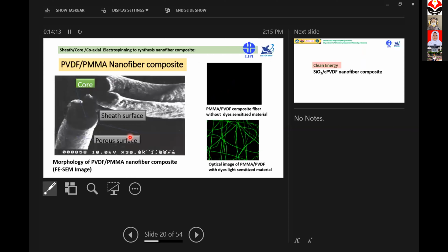Now, how to make nanofiber by using coaxial electrospinning composite. In this case, we try to make a PVDF PMMA nanofiber composite. You can see here, two solutions, one is PVDF, and the second polymer solution is PMMA. Now you can see here, in the core is PVDF, and in the shell is PMMA. So by using this technique, we can make more complex nanofiber composite.